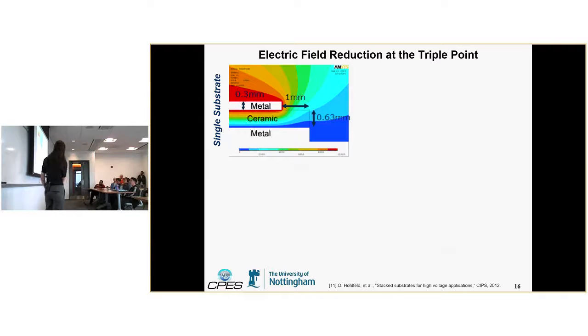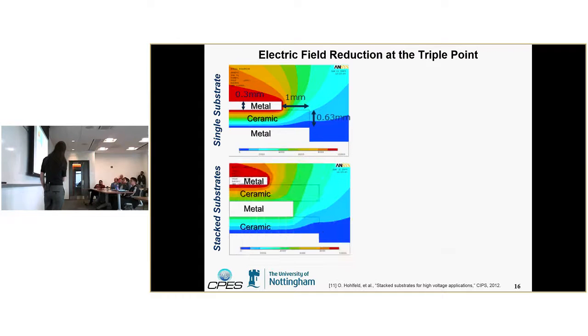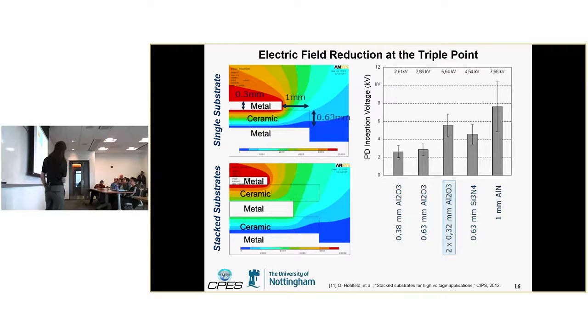It was shown in the literature that for standard metal ceramic metal, this is the electric field distribution. If you stack two ceramic substrates, you can see the electric field is more evenly distributed throughout the two ceramics. They also did partial discharge tests. Basically, they apply a voltage and measure the partial discharge current. The voltage at which the partial discharge occurs is called your partial discharge inception voltage, or PDIV. This is plotting the PDIV for several different cases. The first case is 0.38 millimeter thick alumina ceramic, the second case is 0.63 millimeter alumina ceramic, and the third case is two of the 0.32 millimeter ceramics.